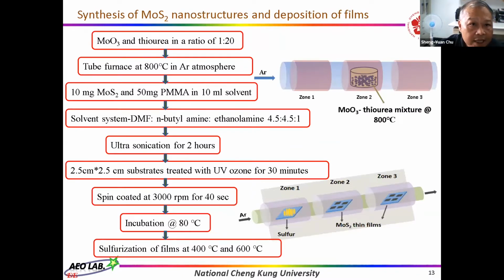This figure shows the synthesis of MoS2 nanostructures and the deposition of MoS2 films. MoO3 and thiourea are used, thiourea as the sulfur source here, and the ratio is 1:20. In the two-zone furnace, the temperature is about 800 degrees for 1 hour, in an argon atmosphere. And then the MoS2 nanostructures were combined with the PMMA and the solvent system, including these three, and then spin coated at 3000 RPM for 40 seconds. And the sulfidization of the films was done at two different temperatures, which are 400 and 600 degrees.